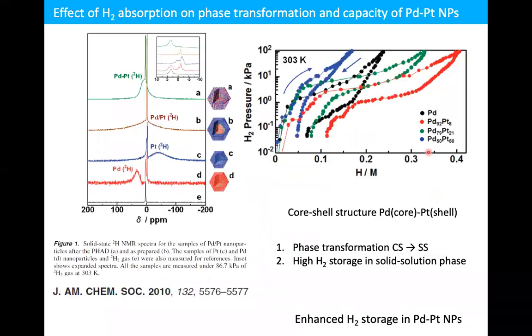Now, if we move to the palladium-platinum nanoparticle, three main observations were found for this system. The first one is that the hydrogen storage property is significantly higher as compared to the palladium nanoparticle. Moreover, after the process of hydrogen absorption and desorption, the core-shell structure gets transformed to the so-called solid solution phase. And in the solid solution phase, the hydrogen storage property is higher as compared to the core-shell structure